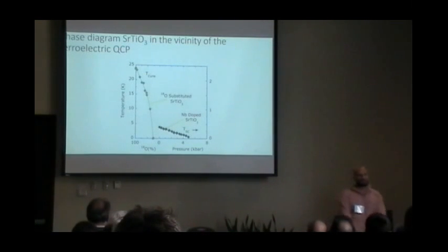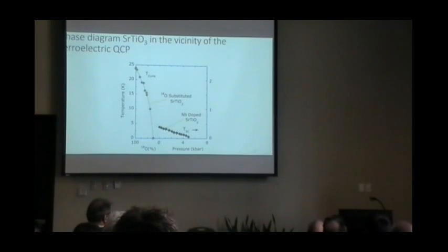What is the phase that extends to 25 Kelvin at negative pressure? So this is a ferroelectric phase. If you have a non-doped material and you put it into negative pressure, or you substitute oxygen-18, then you go to a ferroelectric quantum critical process.